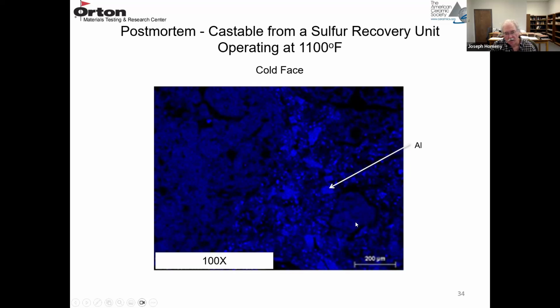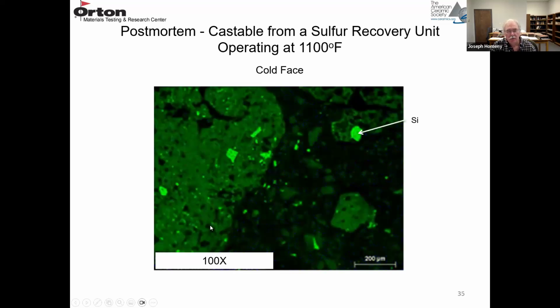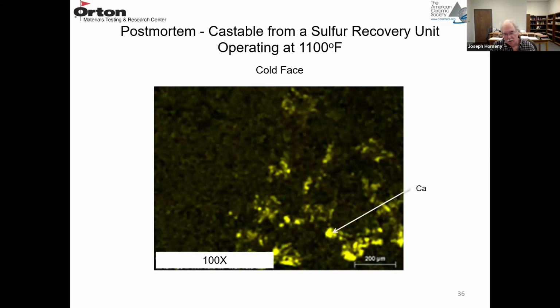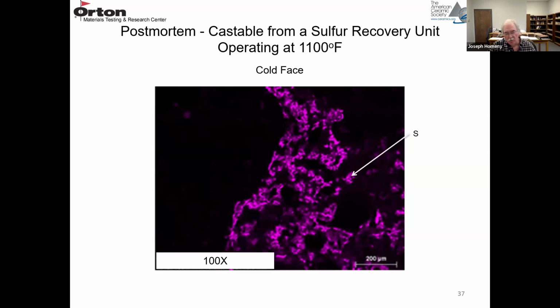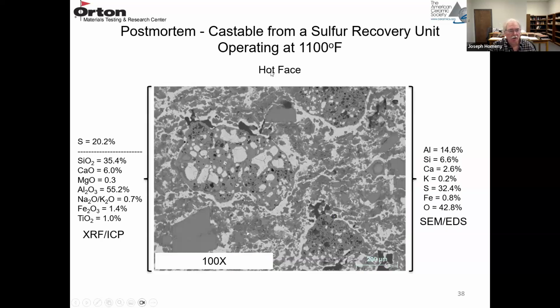Here's another coarser aggregate, and here's a very large one. There's some free quartz in this material, so the brighter green is going to be the free quartz, and then the green that's not as bright is going to be the alumina silica combination. The yellow is the calcium aluminate cement in the matrix. Has to be in the matrix. And then that bright phase I showed you in purple, it's in purple here. That's where the sulfur has diffused into the refractory all the way to the cold face. So then if we look at the hot face, the bulk chemistry by X-ray fluorescence and inductively coupled plasma, XRF-ICP.